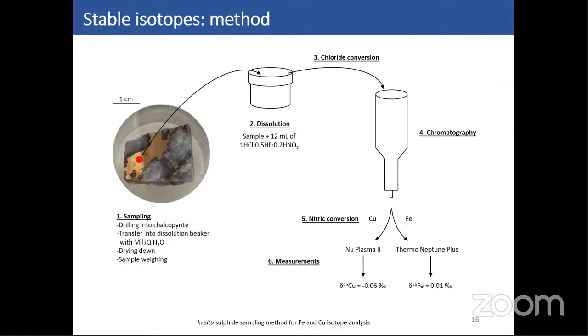So the sample powder is then taken and put into a dissolution beaker. From then on, the procedure is the same for sulfide separates and drilled samples. It consists first of dissolution with a mixture of HCl, HF, and HNO3. The samples are then dried and converted into chloride form, and afterwards the fractions of interest have been separated from the matrix by ion exchange chromatography. And we realized that two ion exchange chromatographies are necessary to obtain a satisfactory purity of the fractions.